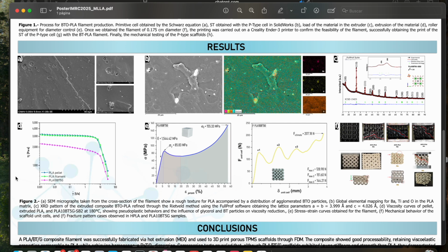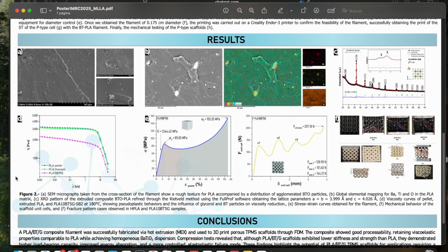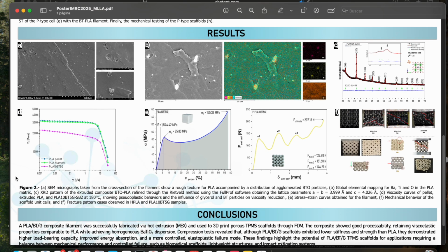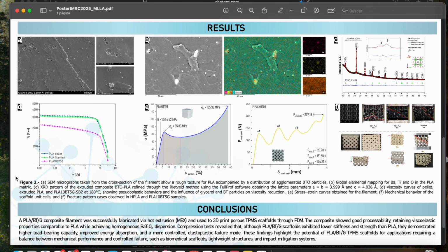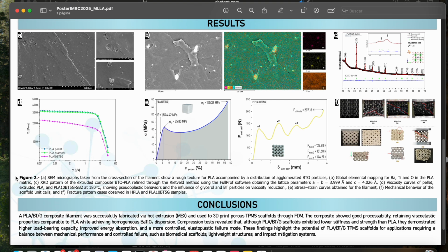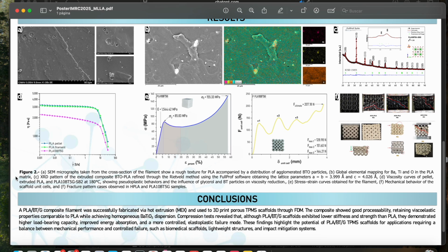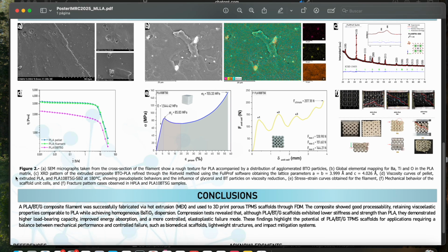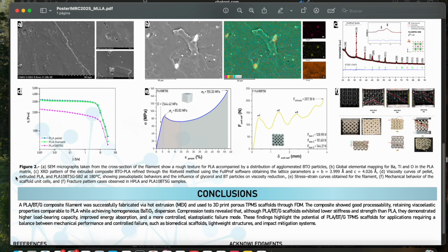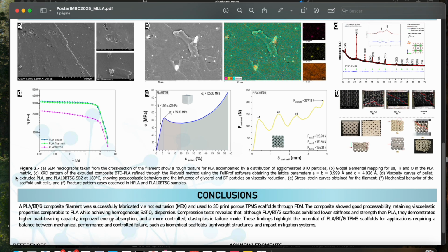The limitations suggest a clear optimization path for future work. Reducing BTO agglomeration via surface treatment or particle size control should increase strength without sacrificing toughness. Adjusting glycerin content will let us trade stiffness against printability, and systematic porosity and geometry studies across TPMS families will generalize the structure property map. On the characterization side, statistical compression results, fatigue testing, and quantitative porosity metrics will strengthen the